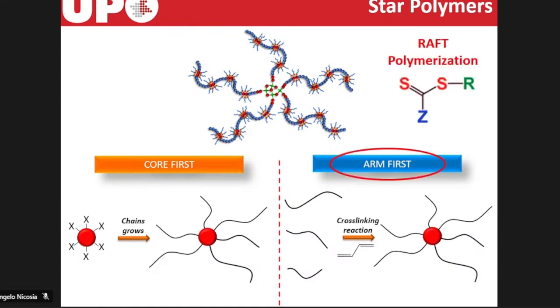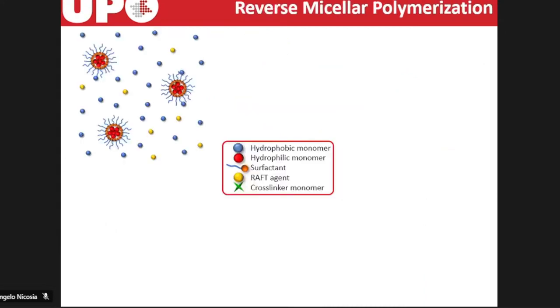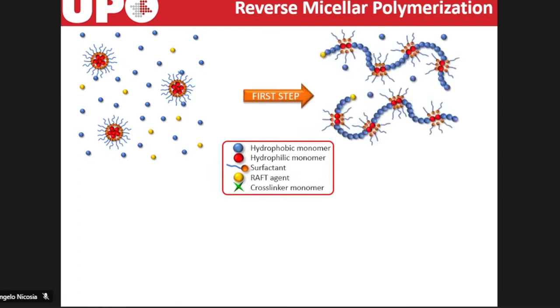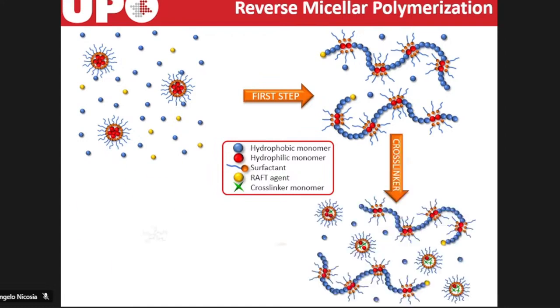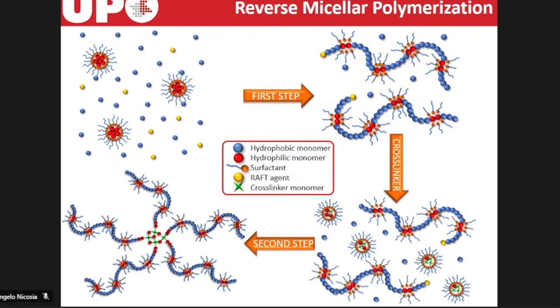In particular, we use a technique named RAFT, and we developed a two-step process. In the first step, we dissolve a mixture of hydrophobic monomer in an organic solvent. We disperse a hydrophilic monomer with the aid of a surfactant, and we use a RAFT agent. At the end of the first step, we obtain polymeric linear arms that are cross-linked together in the second step to obtain the star-shaped copolymers.